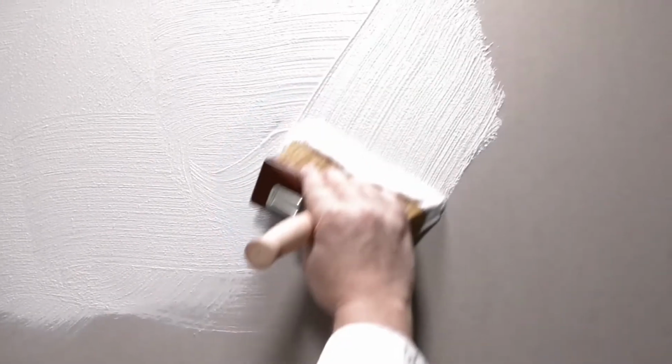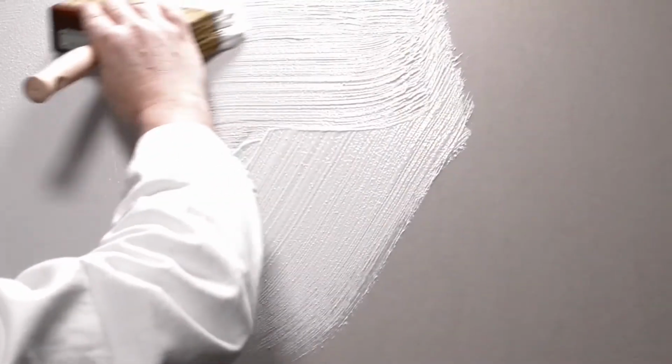10% water. Apply by brush or roller in one coat, watching out to uniformly cover the existing paint or plaster. The final effect will be homogeneous and sandy, a mineral surface compatible and ready to receive your colored lime finish. We recommend to wait 48 hours before decorating with Fondo di Aderenza and 24 hours for Eco Fondo. For further information regarding the application, read the related datasheet.